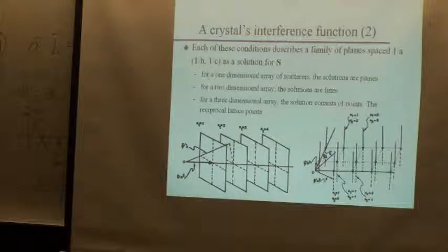It's not because somebody came up with a clever way of drawing something and then we somehow get the instrument to reproduce what we can draw. Okay? It's because of this. Because of the scattering equation, because of the solutions to the scattering equation, because of the fact that three intersecting series of planes that are not parallel to each other will result in spots.